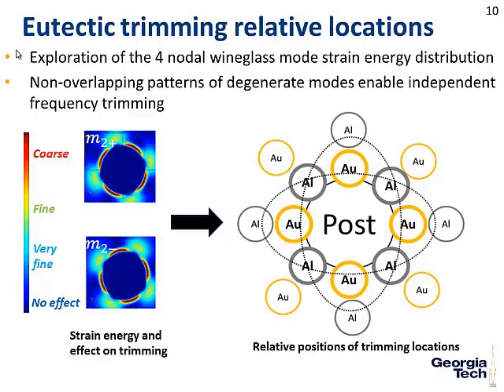And if you do any modification at this location, you can see that this location will have no effect. So what this means is that you can bring the high frequency mode and shift it without touching the low frequency mode, or in a manner that's not very important. But similarly, you can look at the low frequency mode and shift it because here there's no effect. So you can either move the high frequency or the low frequency.